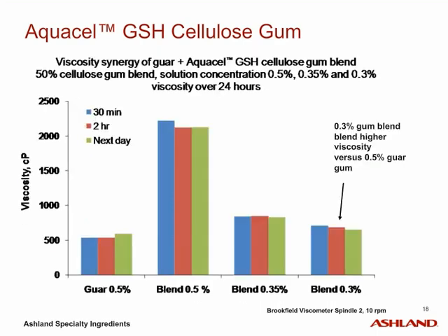In addition to overall synergy, analysis of dosage of the blends was also conducted. In this chart, we're showing blends of 50-50 guar cellulose gum using Aquacel GSH cellulose gum at various dose levels. A 0.3% dose of the 50-50 blend is of comparable viscosity to a 0.5% dose of guar gum alone. Less dose means less overall guar is needed during the supply shortage, and that there is a cost-effective alternative to escalating prices of guar.